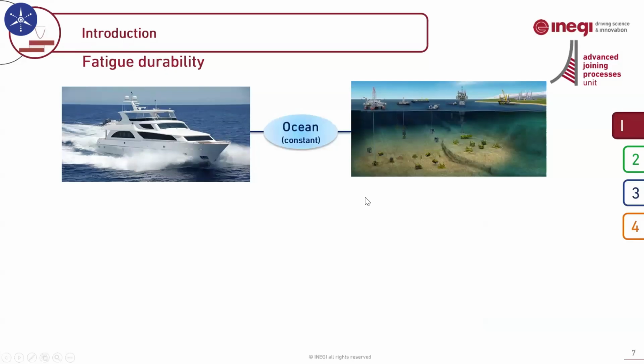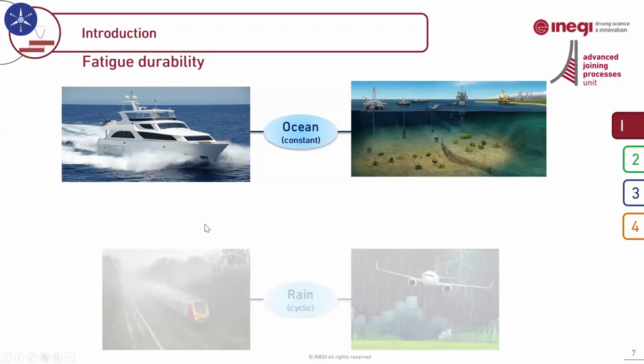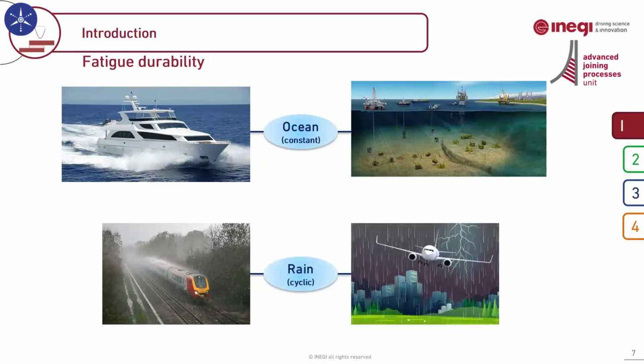Now, imagine your structure is in a humid environment, then you must take into account the effect of humidity, especially for adhesive joints, because adhesives are really sensitive to humidity. And if we make the scenario even more realistic, this moisture level may also vary cyclically, meaning both the loading and environmental conditions are cyclic. You can imagine how complex it becomes to characterize the adhesive's behavior and predict fatigue life under such complicated conditions.